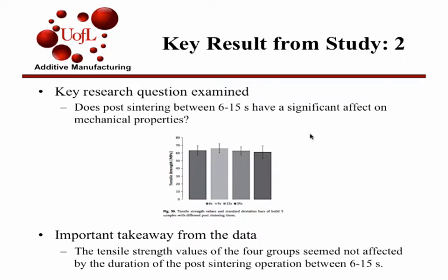The second portion of the study was testing the post-sintering, to see if that had a significant effect on mechanical properties as well. The way the post-sintering works is that there's an infrared heater above, and it turns on for 6 to 12, 15 seconds to guarantee uniform melting between regions exposed. Every time the machine would go over and print something, the infrared heat source would come on and melt the top layer again to ensure that it was uniform. So they did testing at 6, 9, 12, and 15 seconds on each of those layers to see if any of those had a difference in tensile strength. As you can see in this graph, again, there's not a very significant difference in strength from the post-sintering process between 6 to 15 seconds.